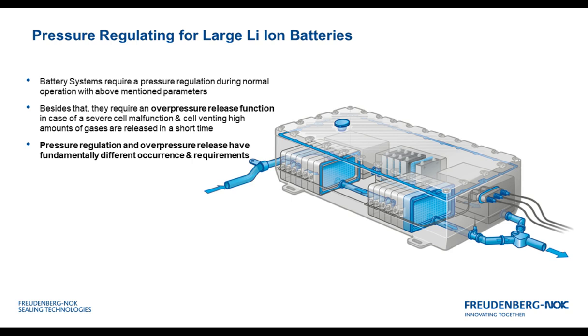One challenge our customers have been faced with is learning to deal with large lithium-ion battery housings. So there's two main functions that are required of pressure regulation for these large housings. And those are, with any sealed housing, you would need a breathable element, so something to allow air to go in and out to regulate the pressure during normal temperature increases and decreases, and a secondary function that is only required for lithium-ion batteries, where when a lithium-ion battery cell decides to vent, it releases a large volume of very hot gas very quickly. And so this, in terms of the housing design, requires an overpressure release function, where you can release this large volume of gas and maintain low pressure within the battery housing.